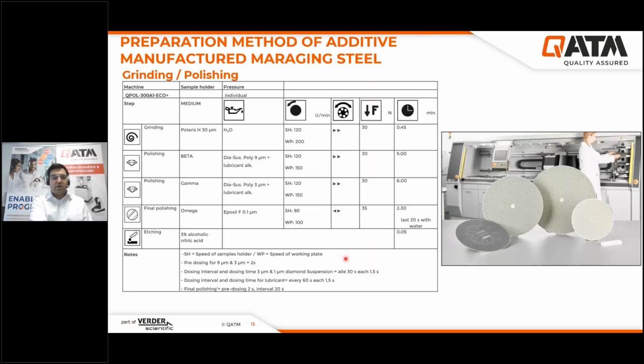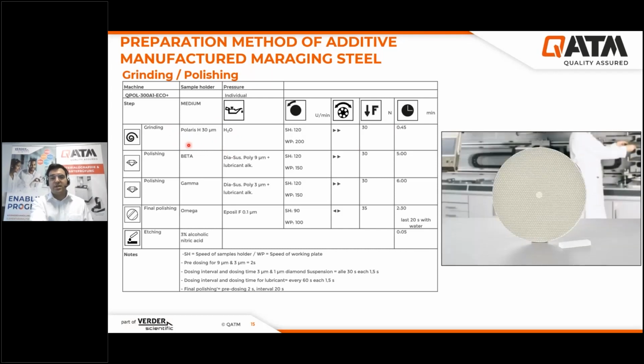Now I want to start with grinding and polishing and show you the preparation methods for different materials. I start with the maraging steel. Here you can see that we start the grinding with Polaris H. Polaris H is a diamond grinding disc with diamond abrasive particles and resin between them. Very shortly, we can have a very plain surface and start with polishing with beta 9 micrometer, gamma 3 micrometer, and omega for final polishing.